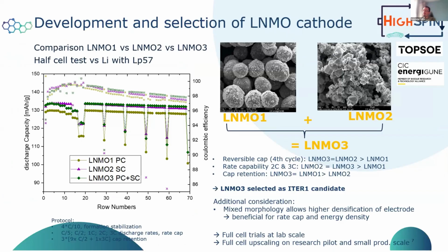And what we found, for example, in this particular case was that it was beneficial for our iteration one to mix two LNMO candidates into what we then called LNMO3. So taking both the spherical particle morphology and the polycrystalline one, because if you look at the graph here, the LNMO3 had overall fairly good performance characteristics compared to the other two. And also from a processing point of view, this allowed higher densification of the electrode, so a higher areal loading.